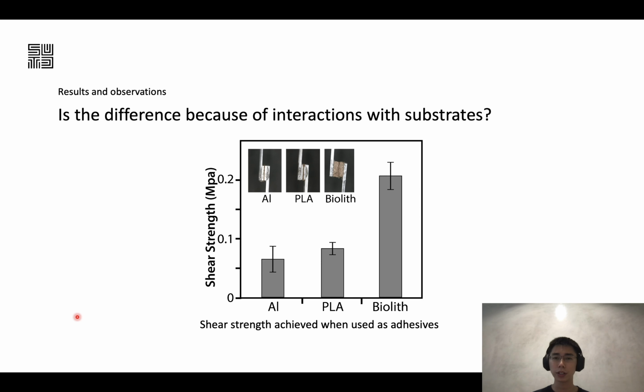Now, our hypothesis or postulate is that these differences might be because of mismatch in stiffness between Biolith and the substrate itself. So an easy way to think about this is that if you have a very stiff substrate on which Biolith is being applied to, when there is a very high hydraulic pressure, the entire substrate, because it's very stiff as compared to Biolith, it would be less likely for the substrate to deform, and in turn, the hydraulic pressure would kind of cause an accumulation or concentration of stress at the repair site itself. And this causes rupture or burst failure to happen